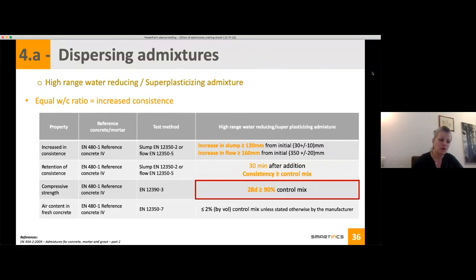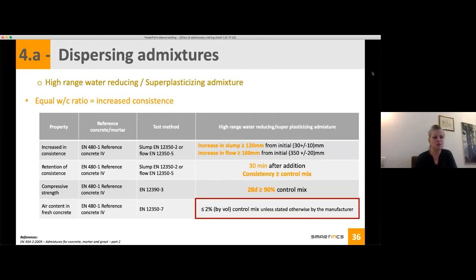Then you also have some specification relating to the compressive strength. You have increased consistency, so same water to cement ratio, which means you have more water available for hydration. So in that case, it's also translated here by the requirement that the 28-day strength should be at least 90% of your control mix. So not 100%, because then virtually your water to cement ratio is a bit modified, but you still could have a good strength. And the same as before, the air content should not be more than 2% extra than your control mix.